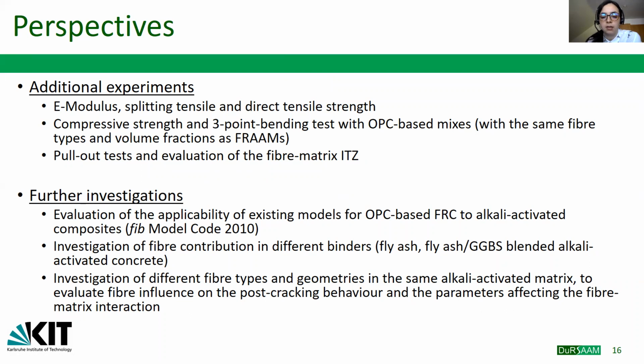In particular, direct and indirect tensile strength tests need to be performed to fully understand and characterize the material and to define correlations between the mechanical properties as for traditional OPC concrete. For this reason, OPC-based mixes with the same fiber types and fiber percentage as the alkali activated matrix need to be cast and tested to evaluate if the same fiber with the same percentage and volume fraction can behave in the same way in different matrices, both traditional concrete and alkali activated concrete.